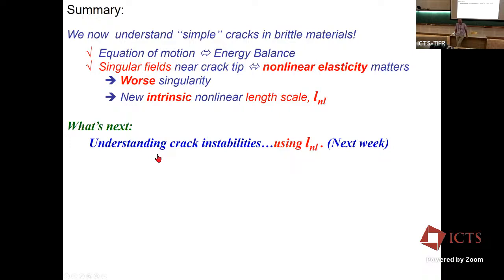We'll take a closer look at branching tomorrow. You'll find that it's not actually a bifurcation. What I hope to show you is that it looks like a bifurcation. You have a crack that's curving, and at one Z location along the crack front you have a perturbation that causes the crack to curve out of plane. The other one goes straight. If you look at both of them from the side, it looks like you have a bifurcation, but it's not.